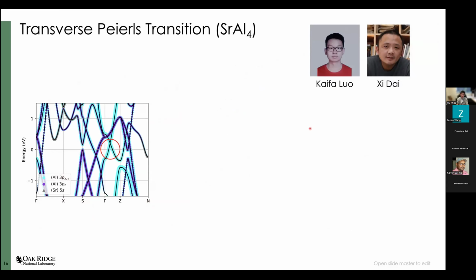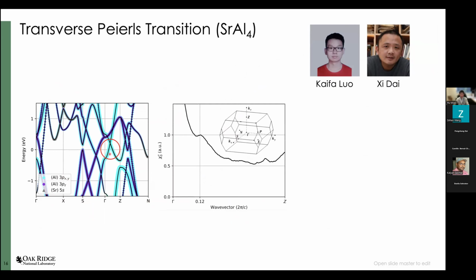Then we can ask what the drivers of the transverse Peierls transition are. So we asked Xi Dai and his student Kai Fa to help us calculate the charge susceptibility. Here shows the DFT calculated band structure. First, we confirmed that near the Fermi level, the electrons mainly have px and py orbital character, as I showed you before. And we can calculate the charge susceptibility along the gamma-Z direction, which is the CDW wave vector direction, and you do observe a charge susceptibility peak at the CDW wave vector.